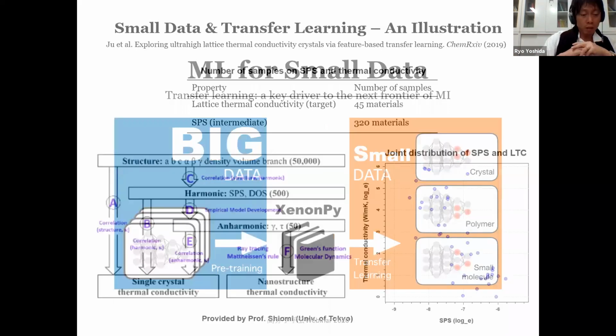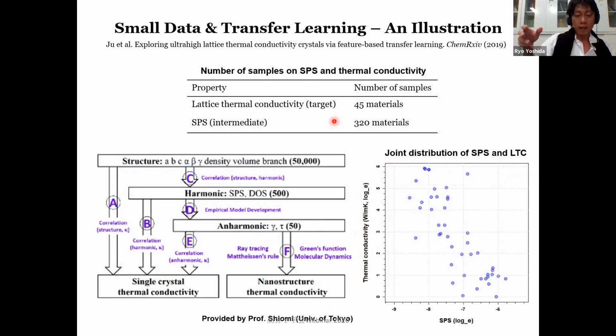This is an example taken from our study. The target is the discovery of inorganic crystals with high thermal conductivity. However, when we started this project, we only had 45 data points on thermal conductivity. So we decided to use an alternative target property, called scattering phase space, hereafter SPS. We collected 320 samples for the SPS, which are used for the source data set in the transfer learning.